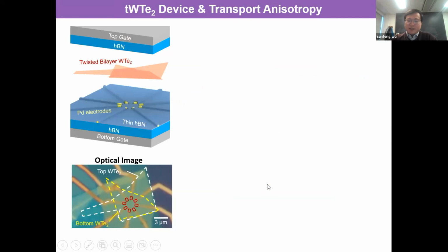And then to study the physics, we fabricate this kind of device in this geometry where we have top and bottom gate and boron nitride fully encapsulate the system to make high quality. The material is kind of air sensitive, so we really have to encapsulate them. And also there are edge modes for the monolayer, right? So a lot of fabrication processes in graphene we cannot do because it's air sensitive. So that's why we have invented this geometry.